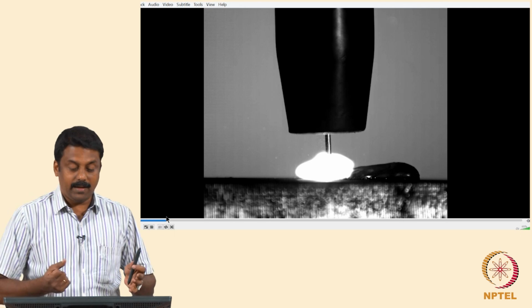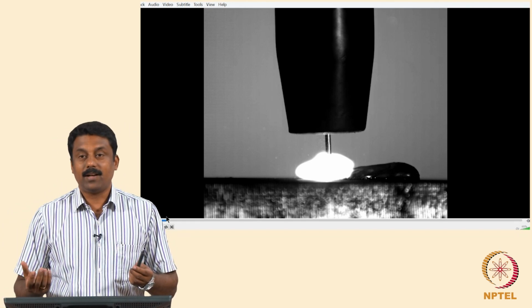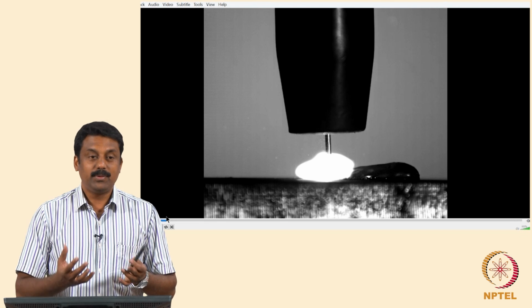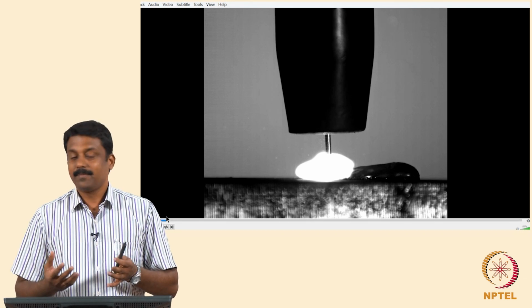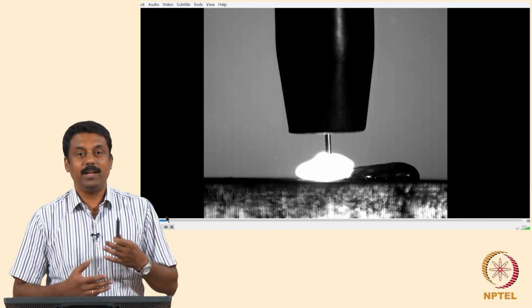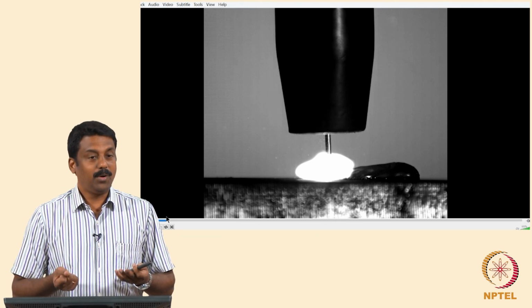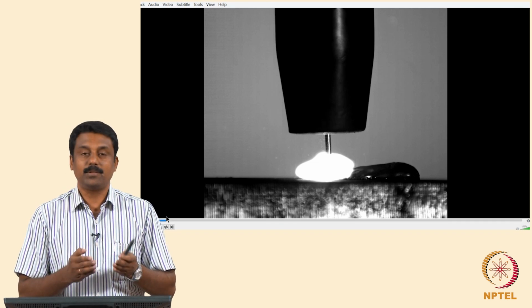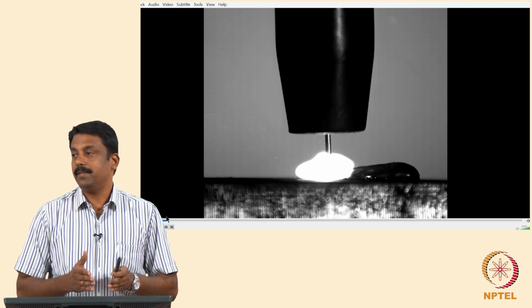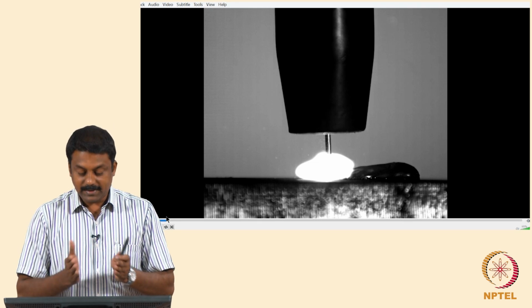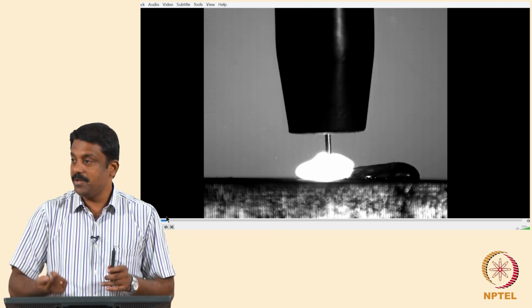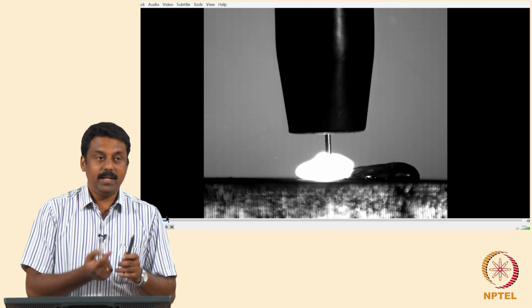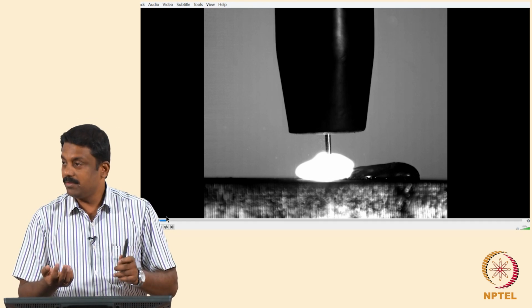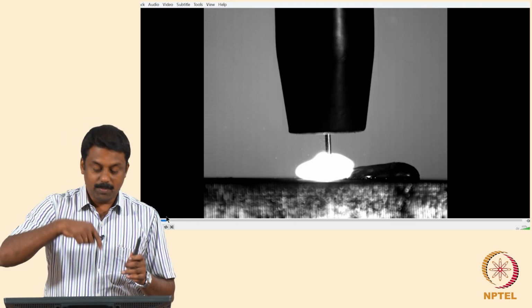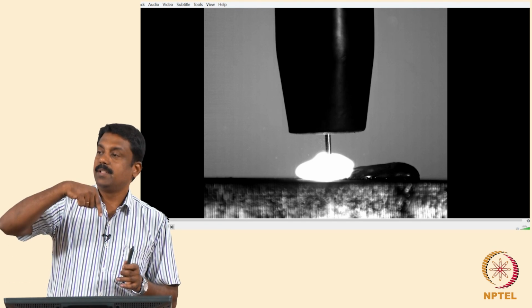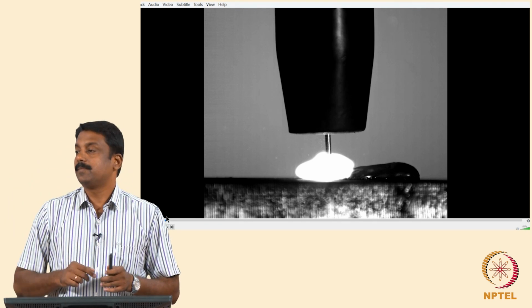So to achieve such a kind of complex metal transfer, the power source characteristics are extremely important, because the power source would also calculate how much it melts. Melting rate should be calculated accordingly. Wire feed rate should also be controlled, so that you can establish the short circuiting at a given defined interval. The moment short circuiting is established, again the power source should measure the voltage of the system, and the moment the voltage becomes extremely small, the current should be switched off, and then the droplet can be detached by retracting the wire back.